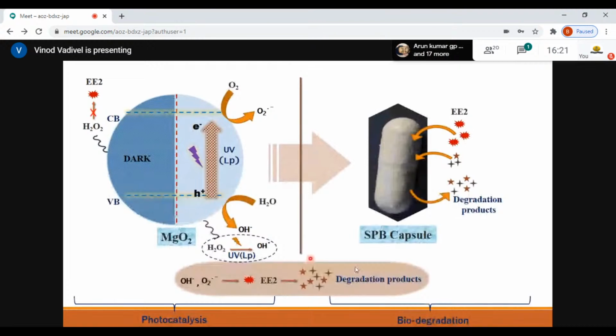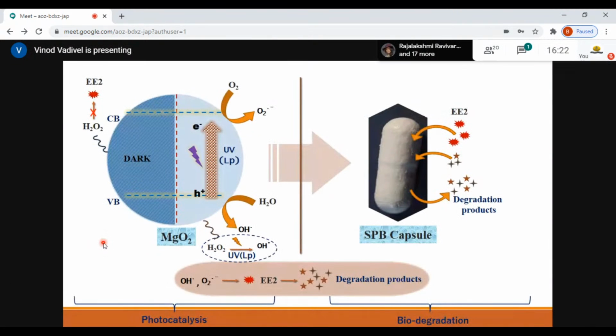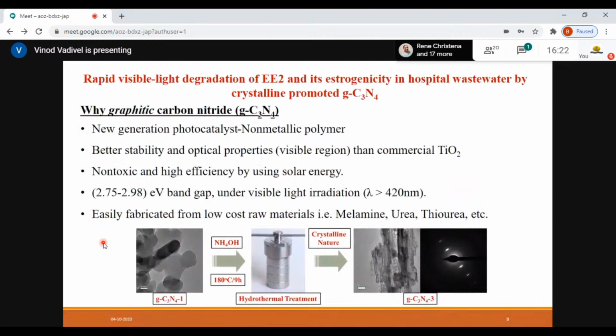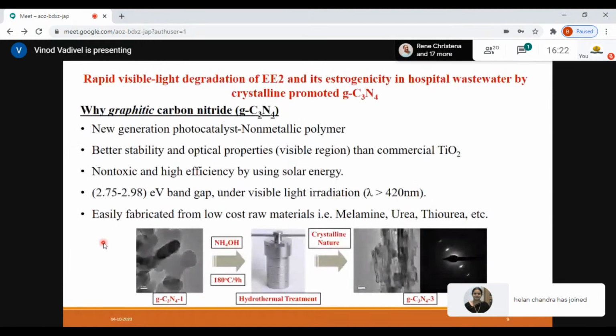So this is the graphical scheme. You can see here, the whole system is photocatalysis with MgO2. So the first phase will be pre-treating EE2 with magnesium peroxide in low pressure UV. Then this effluent is transferred to the capsule system, and here you have your degradation products coming around. And this is a combined technology of photocatalysis and biodegradation process. When we had that system worked out, we published that paper in Materials.